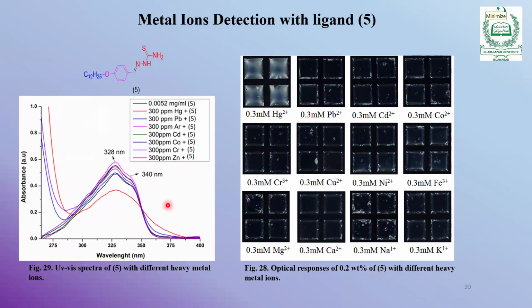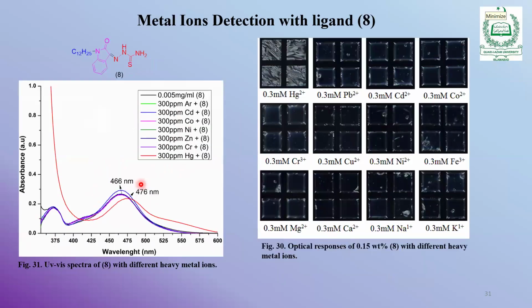And at the same time, we took the visible spectra of these solutions. What is observed is that with the mercury ion, we observed some bright texture, with the others, no texture is observed. It is also evidenced here that with the mercury, we observe some shifting of the UV visible band, and the other metals, they give you almost same type of pattern. So both the results, they are in coherence with one another.